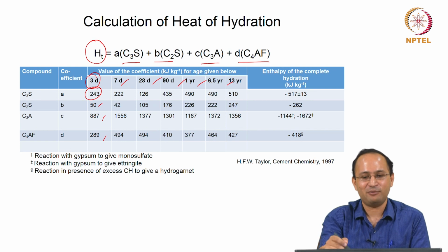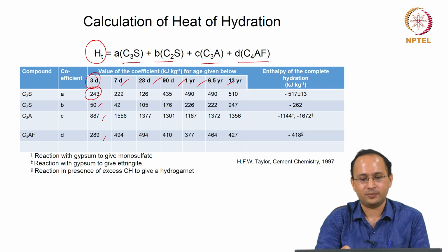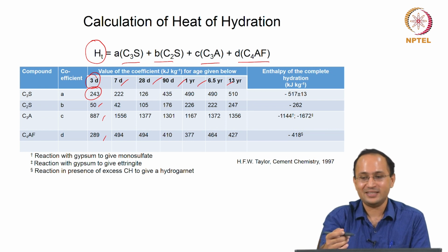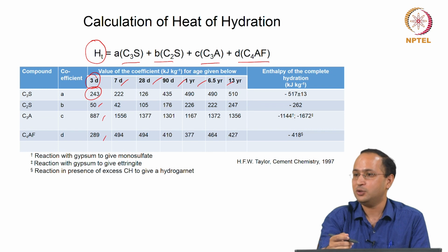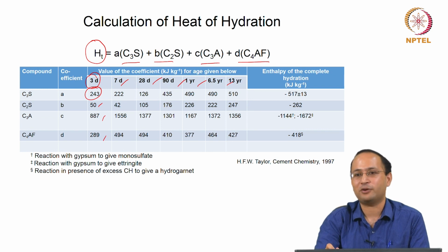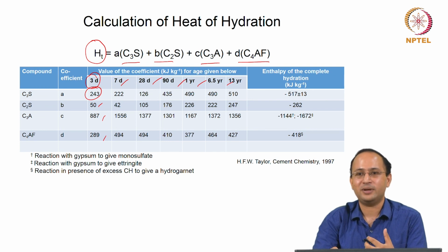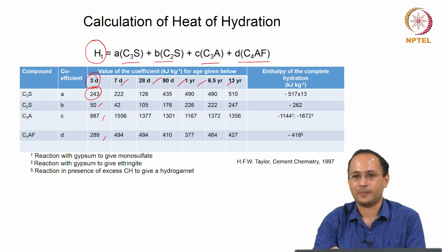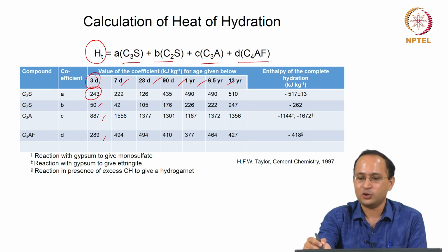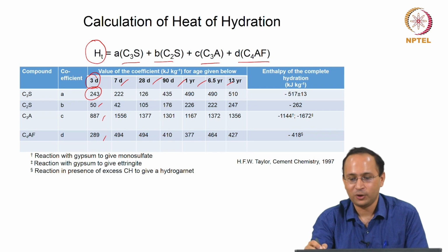In this study they basically looked up to 13 years, right. So this simple relationship can be used to calculate the heat of hydration, right. It is nothing but the contribution from individual phases, right. Also you see here enthalpy of the complete hydration, that is very important, right.